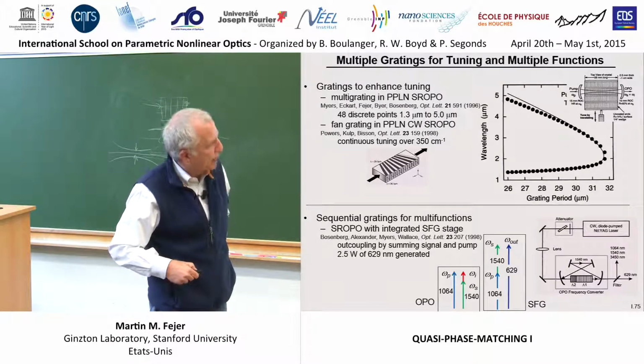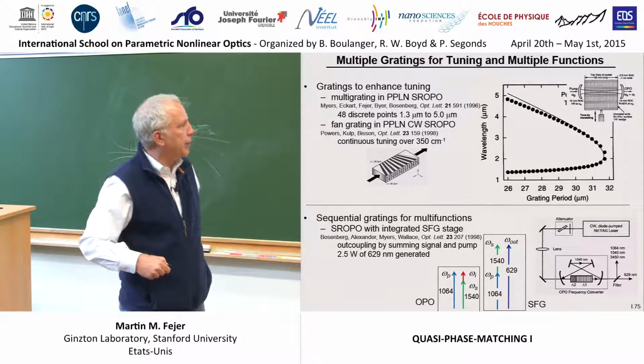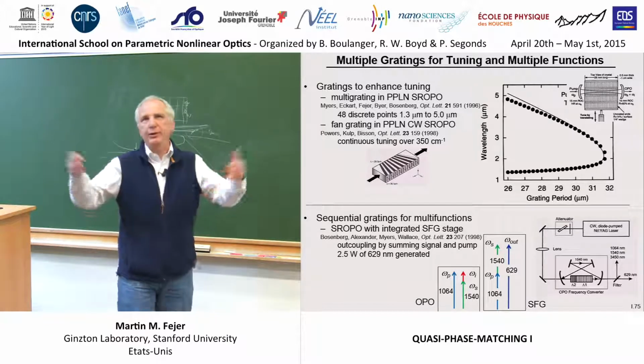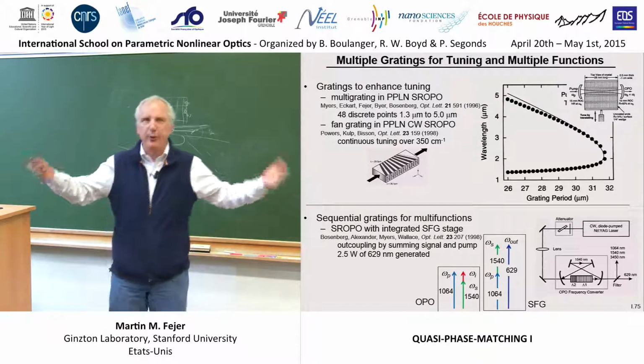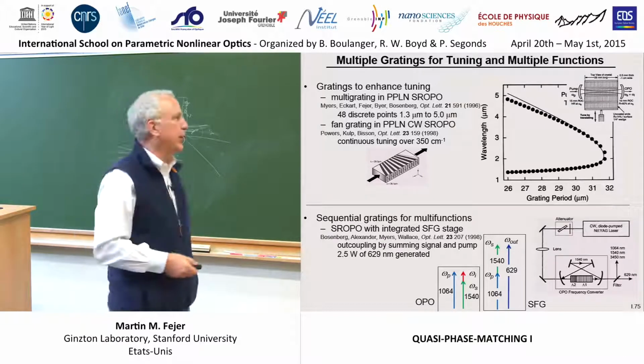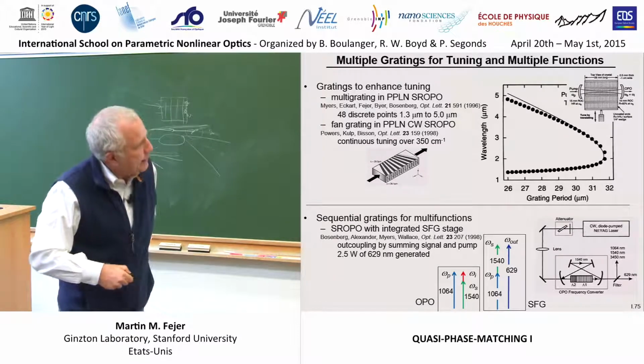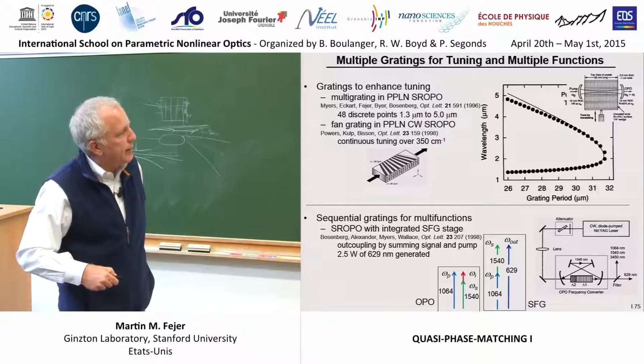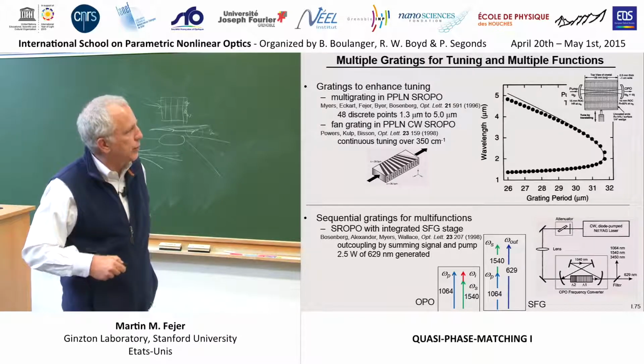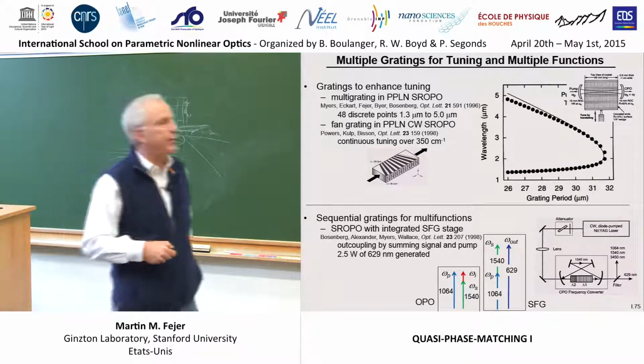The second grating sums the pump wave with the resonant signal wave to make a red wave at 630 nanometers, which they needed for some photodynamic therapy or something. And the second grating is, of course, with a period chosen to phase match this process. The first grating has a period to phase match that process.